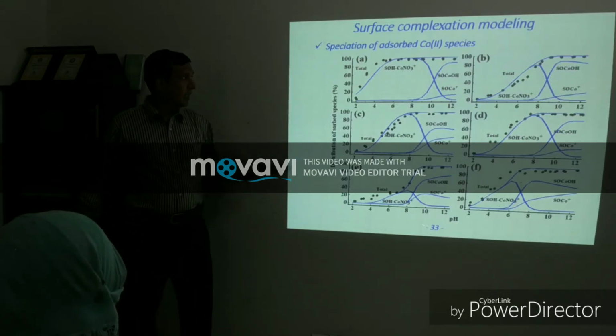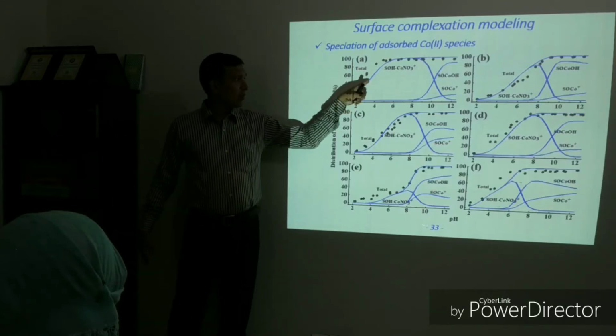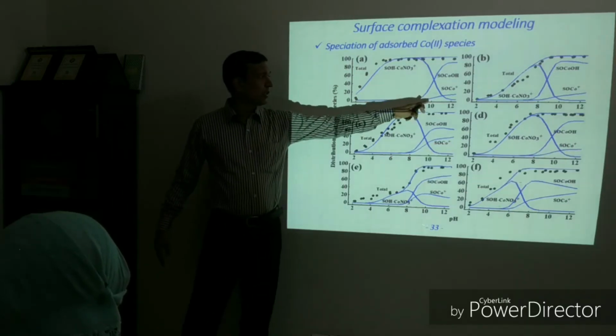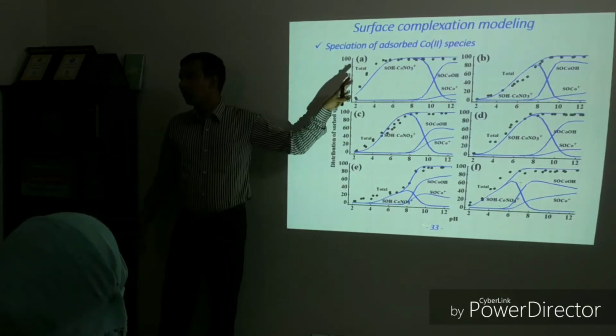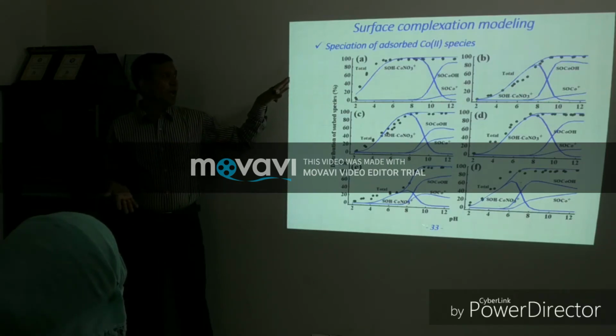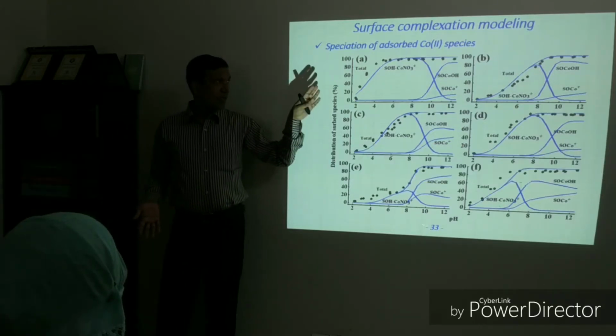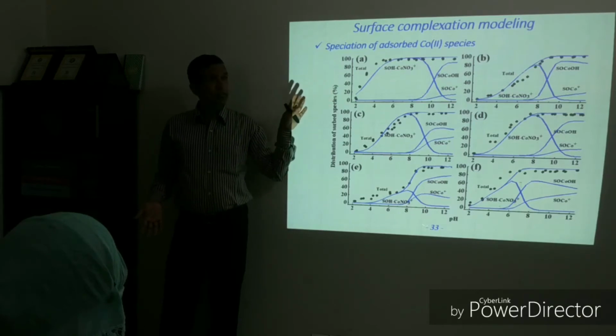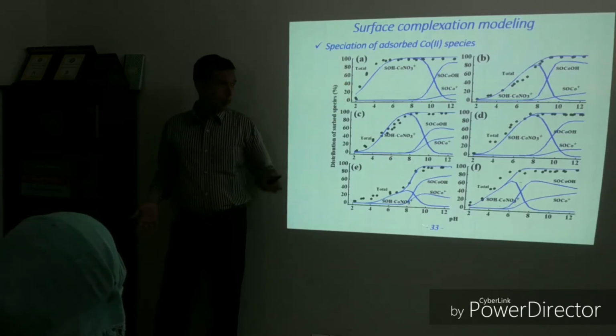Here is the speciation of adsorbed cobalt species. This one is outer sphere complexation, and these two are inner sphere complexation. So from this speciation, we see that cobalt mainly adsorbed onto the surface by forming outer sphere complexation at low pH values. On the other hand, inner sphere complexation at higher pH values.